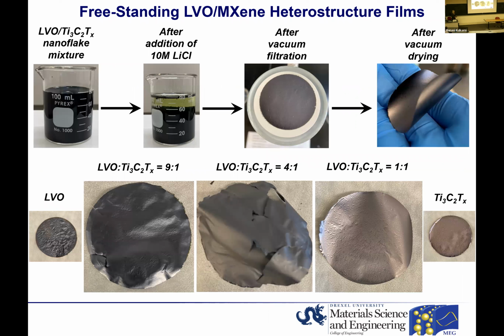And in addition to that, we of course also want to integrate our bilayer vanadium oxide with MXenes, because MXene exfoliation processes are already very well developed. These are highly conductive materials, which, unlike graphene, can introduce some redox activity into the final product. And that might allow us to also obtain much higher capacities compared to the two-dimensional heterostructures we've made with the graphene oxide.